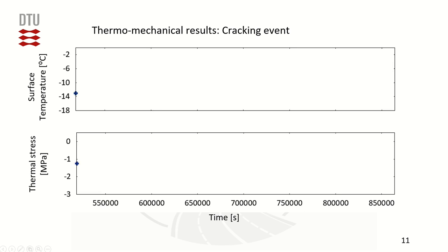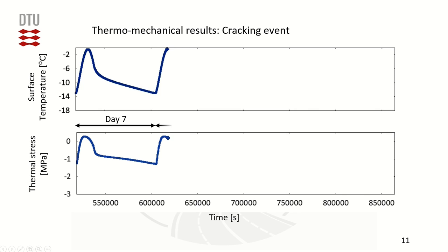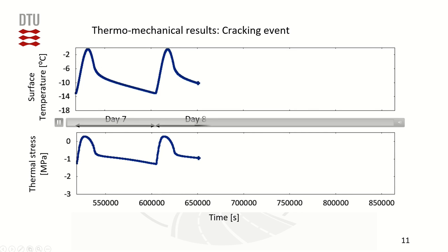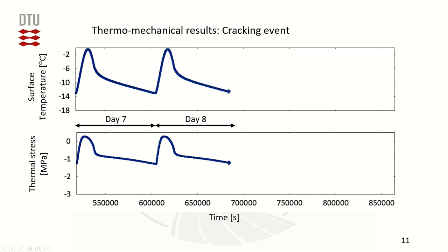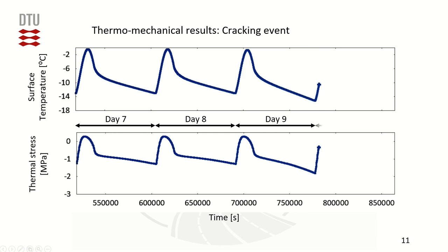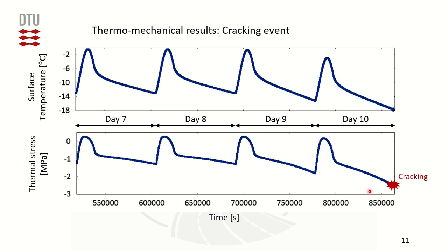Based on the presented thermomechanical model, the thermal formulation was applied during 10 days to calculate the surface temperature, and then the mechanical formulation was utilized to quantify the thermally induced stress at the surface of the half space. The aforementioned air temperature decrease aims at generating thermal stress which exceeds the defined half space material tensile strength of 2.5 MPa. The presented chart displays the evolution of the surface temperature and the thermally induced stress for the last 4 days of the simulation. As can be seen, for the selected parameters of the mechanical formulation, the thermal stress exceeds 2.5 MPa at the end of the 10th day, meaning a low temperature crack would have occurred for this thermomechanical scenario.